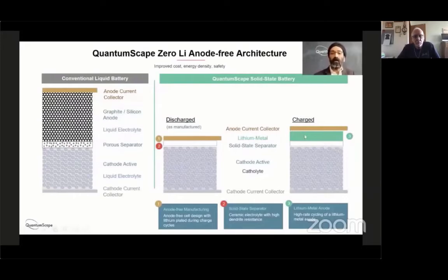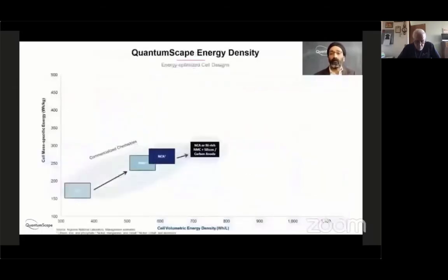So just looking at this slide, you can see that the solid-state lithium metal anode case is much more energy dense than the conventional lithium-ion battery, because it doesn't have all the space and mass and volume required for the carbon or carbon silicon anode. That's the core reason for the advantage that solid-state batteries provide over lithium-ion. And if you do the math, it turns out that you can end up with on the order of 1,000 watt hours per liter with this solid-state architecture, which compares with an energy density of around the 700s in terms of watt hours per liter for conventional lithium-ion technologies.